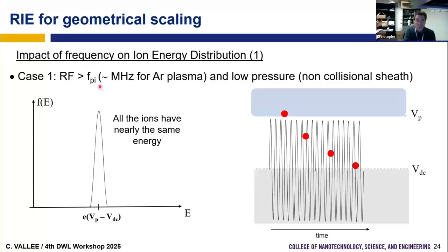Since the frequency of the ion is very low compared to 13 megahertz, what does it mean? It means that the time it takes for the ion to transit through the plasma sheath, so to go from the plasma to the substrate, is very long compared to the time of the oscillation because the frequency is very high. So the ions are not sensitive to any instantaneous value of the peak-to-peak voltage.